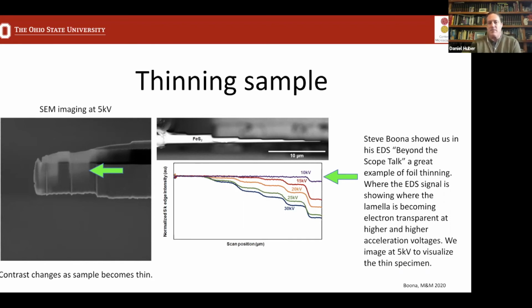And so the sample will start to appear bright when it gets really thin. We know that happens roughly around the mean free path of the 5 kilovolt electrons, in the neighborhood of about 100 nanometers in most materials. So as our sample becomes a little bit less than 100 nanometers in thickness, we're going to see this brightness change with a 5 kV accelerating voltage. That's why we pick 5 kV. Steve's really shown a good example here with his EDS data of where that transmission would be happening at 5 kilovolts.